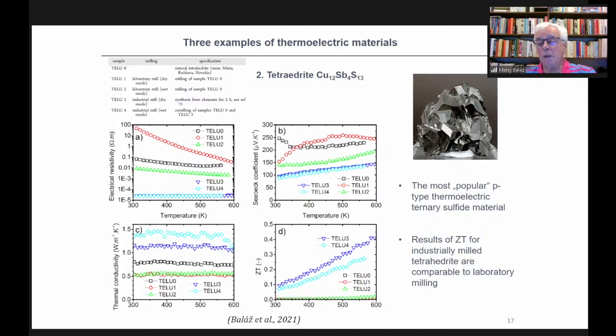And we processed it in several modes and published it, but you can see here a table with experiments where samples were designated as TELU. And in principle, again, if you look at ZT, the values for TELU 3 and TELU 4 are the best ones, and TELU 3 and TELU 4 in this table are all the time connected with industrial milling. So the results, we can say, are even better than working in laboratory mode.